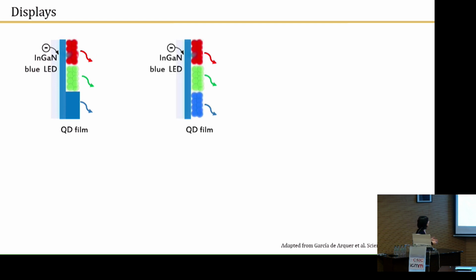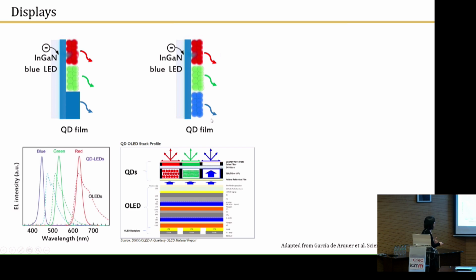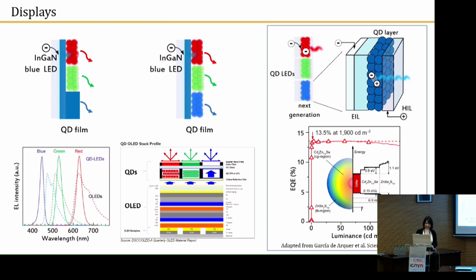Other configurations are being studied or implemented to have smaller quantum dots emitting in the blue, and other combinations, like for example Samsung in 2021 decided to include a combination of the Q dot emitters with OLED, organic light emitting diode, in their TV panels. The next generation of TVs, in principle, is to get these particles, instead of being optically excited, to be electrically excited. This means to inject charges, to inject electrons and holes in such a way that the particles can emit without being photoexcited. And this is still a bottleneck in the industry, as far as I understood. And I gave you the reason why this is a bottleneck.